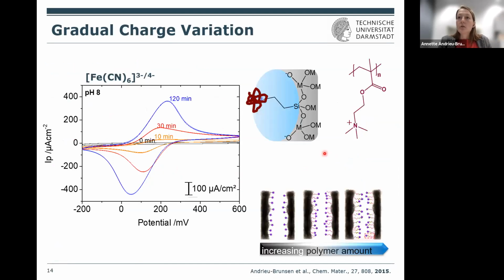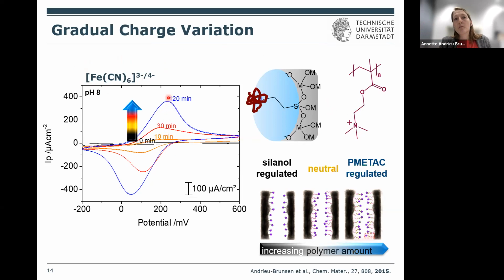But if you use controlled polymerizations, and now you choose not the pH responsive polymer, but the strong polyelectrolyte, and this is the next step we did, you can control the charge density in the pores by the polymerization time or energy. And this is actually what you see in these cyclic voltammograms. So again, it's a negatively charged probe molecule that is electrostatically attracted by this polymer. And you see along the polymerization time that the IP increases, so the amount of ions in the pores increases. And what you basically do is that you go from a silanol regulated pore over a neutral pore to a polymer regulated pore. And then with increasing charge density, increasing ions are present in that pore.